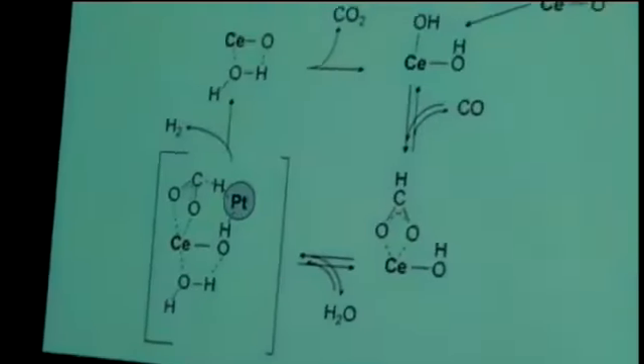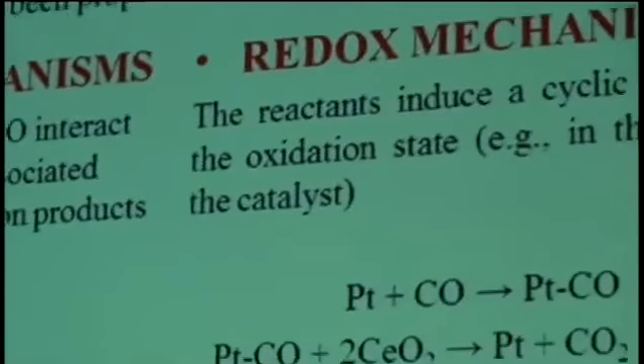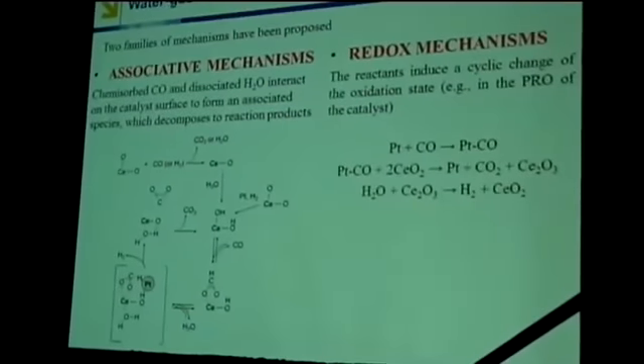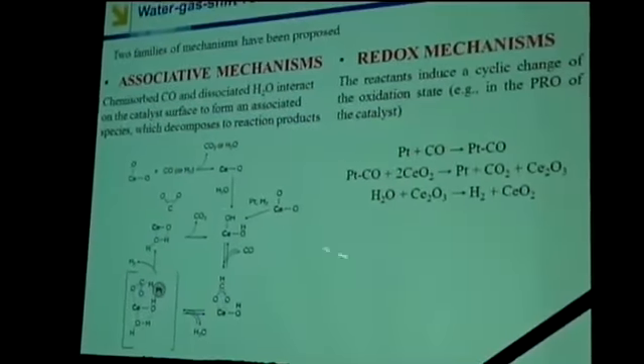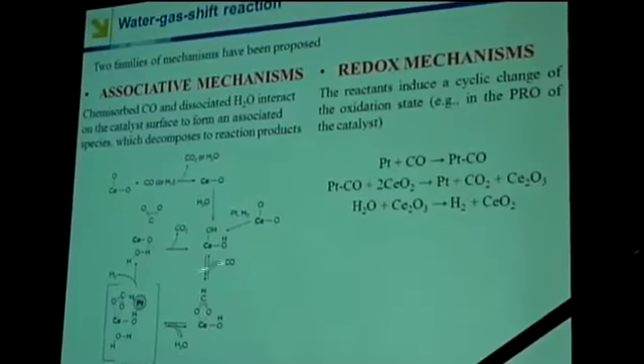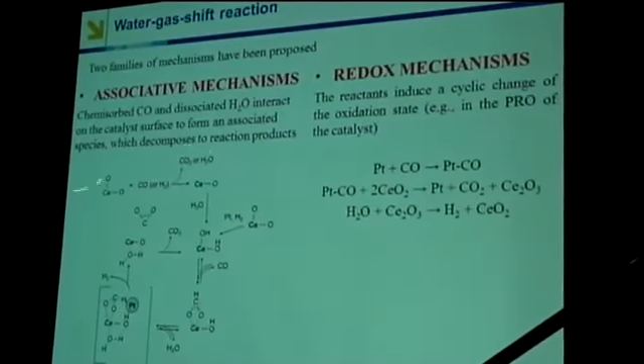Then we have a family of associative mechanisms which involve adsorbed intermediates such as formates or carboxylates that have also been proposed, even oxalates. And in this case, the defects are also involved. Water is dissociated on the vacancies to generate bridging OH groups, which then react with CO to form the associated intermediate. And this mechanism, which was proposed by Shido and Iwasawa in the early 90s, has a rate-limiting step which is facilitated by steam.